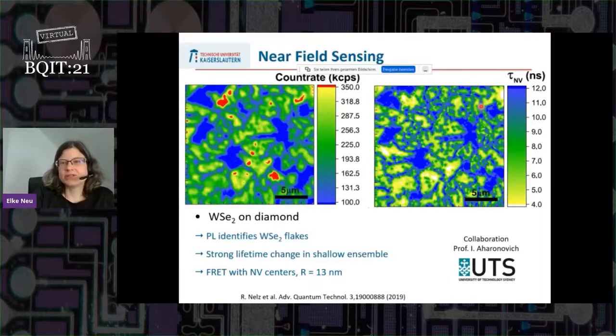And now you switch to the lifetime imaging. So here you image the excited state lifetime of the NV centers. And you can see here, well, you get almost the same picture. Where such a flake has been positioned, you see that the lifetime of the NV center is going down. So you see clearly this transfer of energy from the NV center to the tungsten diselenide flakes.